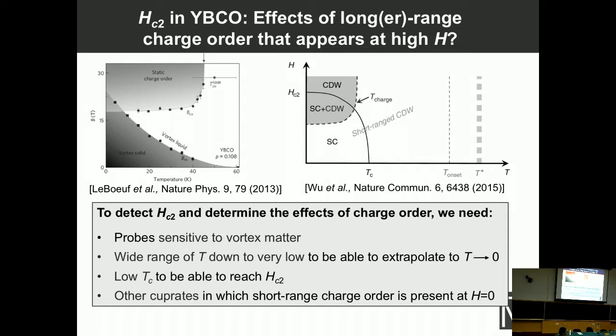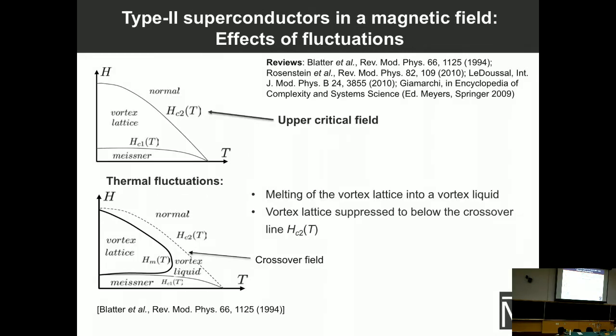So we have accomplished all of this, and before I show you our results, I would like to remind you of some of the things that we know. What we do know is that cuprates are type 2 superconductors, which means that the magnetic field penetrates the material in the form of a solid lattice of vortices, in this mixed state, up to the upper critical field. We also know that thermal fluctuations do melt this vortex lattice into a vortex liquid, such that this vortex lattice is suppressed below what is now a crossover field HC2.